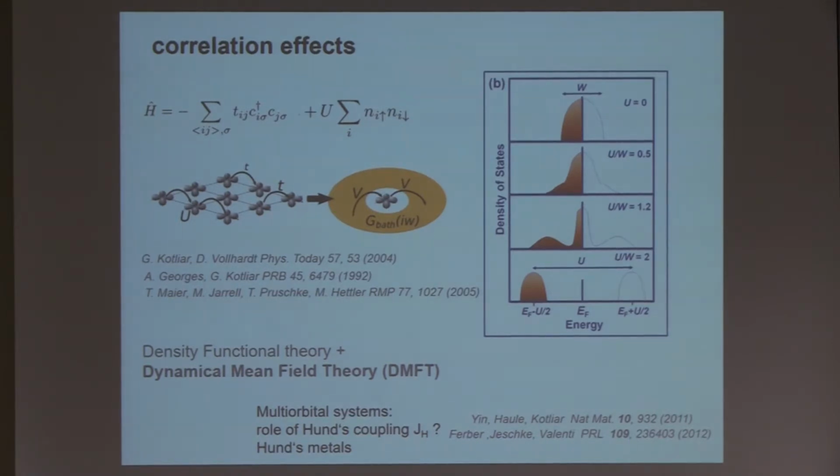What is important is this dynamic interaction, because it gives you an exact description of the local correlations in these materials. So with this method, you have a good description of the local effect of correlations. And now the idea is to assemble together this inclusion of correlations with density functional theory, which gives you a basis of the chemistry that is important in your material.